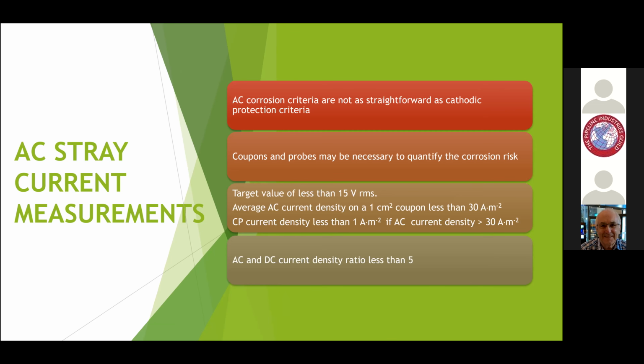And there are basically 4 sort of criteria available. The first thing we aim to do is to get the value down to 15 volts or less. And you might see here that I've been careful to say RMS. That's for electrical people, that's very significant. It means that it's an average value. It's the root mean square value of the voltage, because that's important to us in this context. So the first thing you do is apply some mitigation to get it down to less than 15 volts, even though for touch potentials, you can live with up to 50 volts or 60 volts, depending where you are. However, under certain conditions, you can have AC corrosion with only 5 volts. So we can't apply that 15 volts as a universal panacea, but it's the target value that we always aim for to begin with.